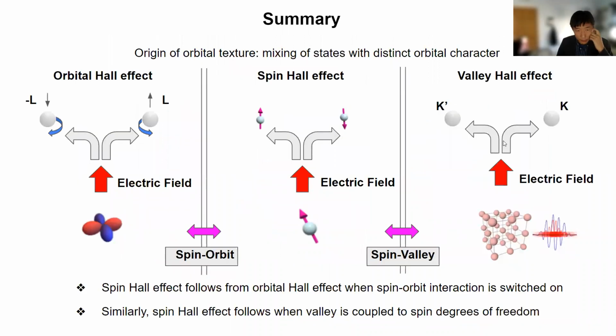So in summary, we look at the spin Hall effect in different material systems, and we look at two particular systems. One is the TMD, and we discuss how the valley Hall effect can result in a spin torque that you can use to switch a magnet, and that spin Hall effect is enabled because of the spin valley locking. And then we also look at twisted graphene on TMD. In this case, we show that the spin Hall effect's underlying origin comes from the orbital Hall effect.